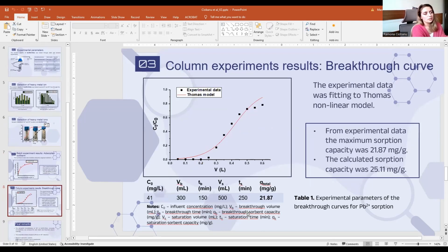So in the column experiments results, the breakthrough curve was a good fit to the Thomas nonlinear model, and the sorption capacity was almost 22 milligram per gram. This means almost 4 times higher than the sorption capacity of lead from batch experiments. So this means the dynamic experiments show a good applicability for the real scenarios from a wastewater treatment plant.